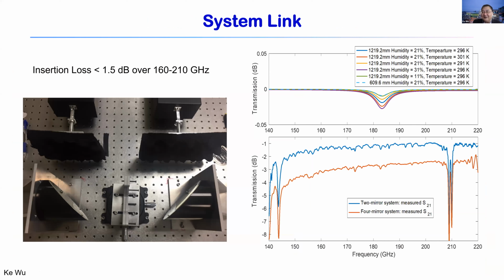As I said, we want to have the optic path loss as low as possible. For this, over the entire system measurement band frequency of interest, we look at the insertion loss from port to port, about 1.5 dB loss. So that's pretty good for a 2-mirror system. A 4-mirror system is roughly doubled, not really doubled, but about doubled. So it's a good system.